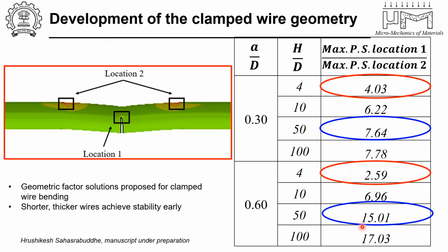So what this tells us is that for shorter wires, the stresses at the edges become concentrated and sort of take away the driving force from the crack tip at the center. And because of which the driving force for crack growth goes on decreasing as we move to longer crack lengths. But this sort of advantage that is provided by the shorter wires goes away when you have longer wires, because now you are very far away. The boundary condition is so far that the specimen almost behaves like a tensile specimen. It does not see the effect of the two edges, and the crack continues to grow in an unstable manner.